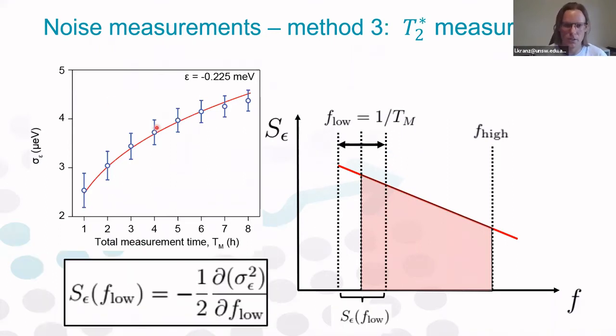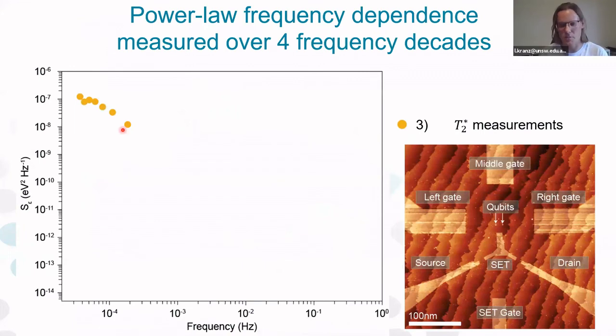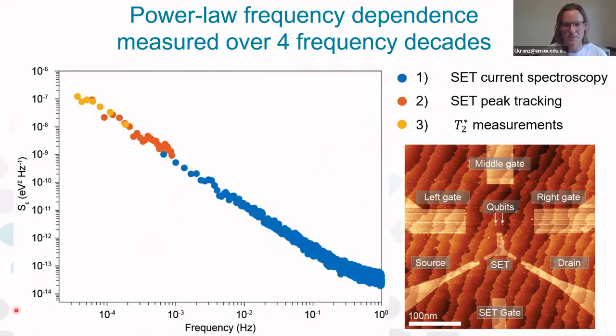But we actually went one step further, and knowing the exact increase of noise with time, we can calculate the exact spectrum of noise in this frequency regime, over which we're changing the lower boundary of the integral. So these are the results here. By changing the total measurement time, we're able to measure the detuning noise spectrum in this very low frequency regime. And this is great because now we can compare this data with the previous two methods that I described earlier. So this is the combined noise spectrum in this device.